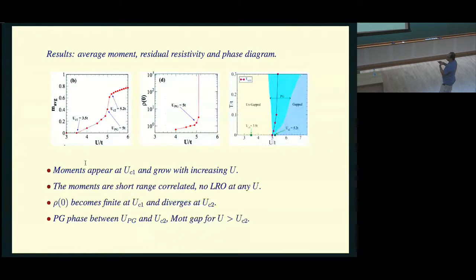They appear at UC1, grow with increasing U, and there is a sharp change beyond which it seems to tail off to 1 slowly. If you examine not just the size of the moments, but the structure factor associated with them, there is no long-range order. So within this picture, it generates what one would call a classical spin liquid of small moments here and large moments here. Because there are disordered magnetic moments in the background, the resistivity becomes finite in the ground state.